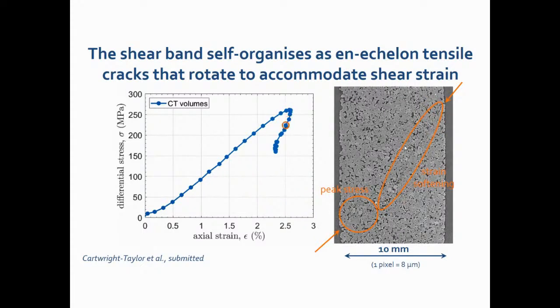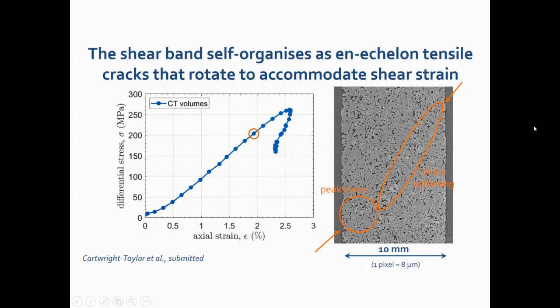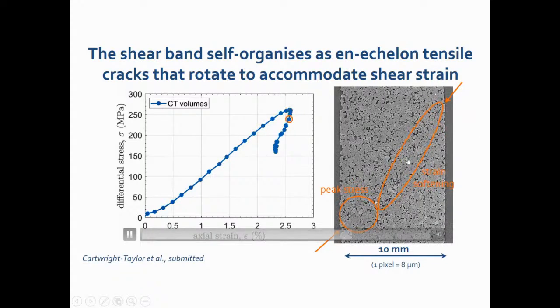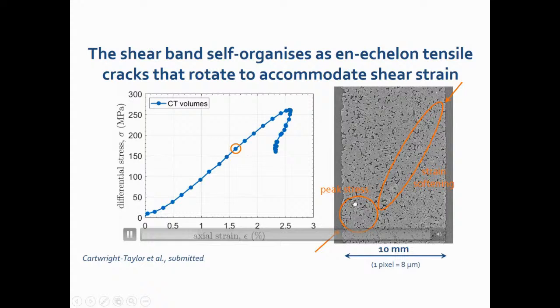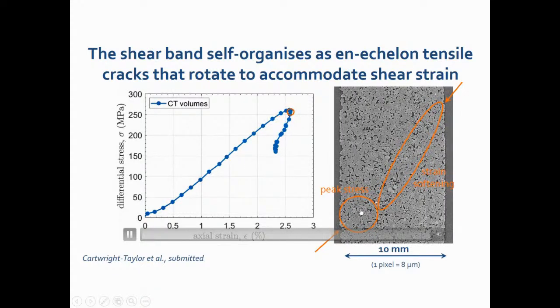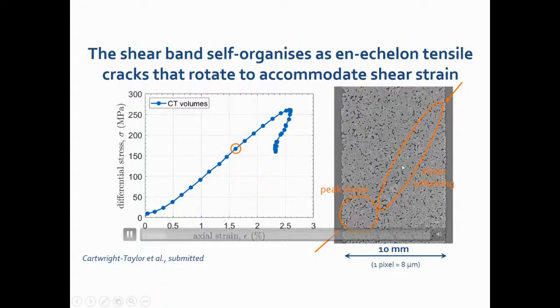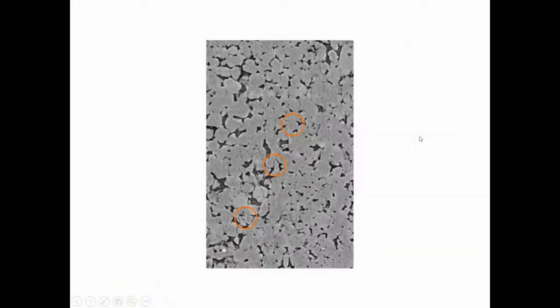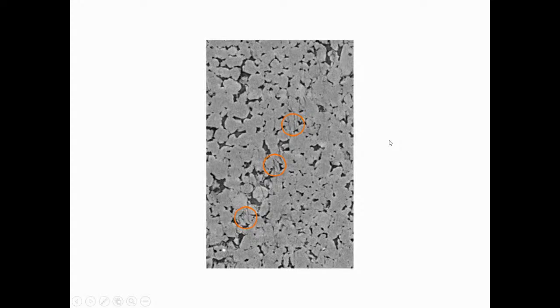So I'm going to, you can see that the strain softening is associated with this coherent shear across the band here. This zone is being damaged more at peak stress, and then it goes into this organized failure here. So I'm going to walk through one by one. It's like a slideshow. And we're going to look at specific features in the starting material. And you see how quickly everything self-organizes along the shear band. Okay, the previous time step to now. Your eye is very good at seeing correlations.